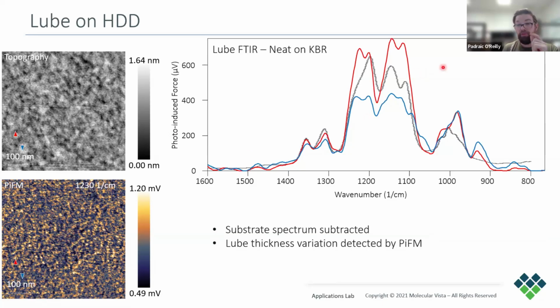And so the average substrate spectrum is subtracted from these lube on a disc spectra, and you can see excellent correlation with the black neat lube FTIR spectrum. So even with this very thin layer of lube, we are getting FTIR-like results.